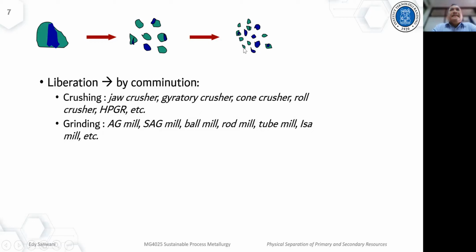Maybe we need to reduce the size of particles from mining activities, say a particle having a size of, say, 80 centimeter. And then we need to do comminution until, for example, 100 micron, because we need a particle of 100 micron to have a reasonable degree of liberation. So then, how many stages of crushing, how many stages of grinding, that's what we need. We have to do some testing, and then after testing, we can design the stages of crushing and grinding.